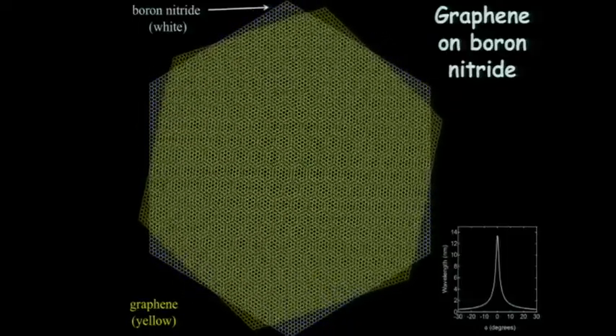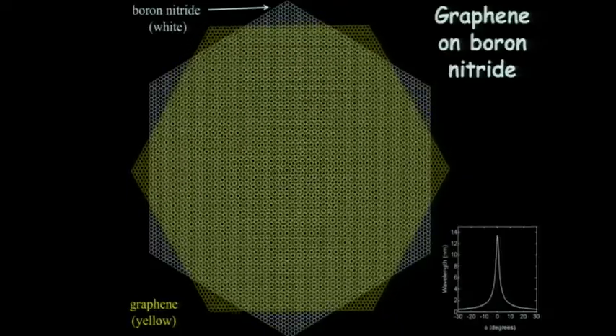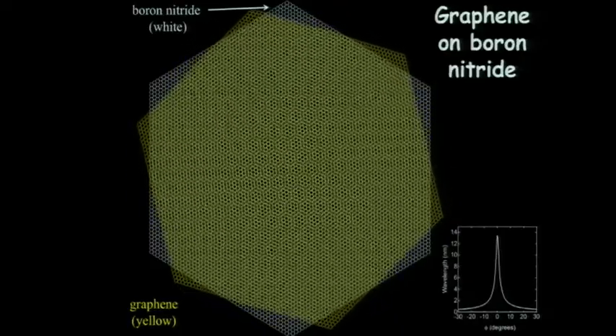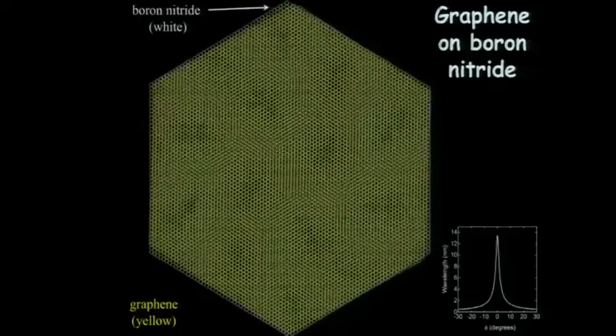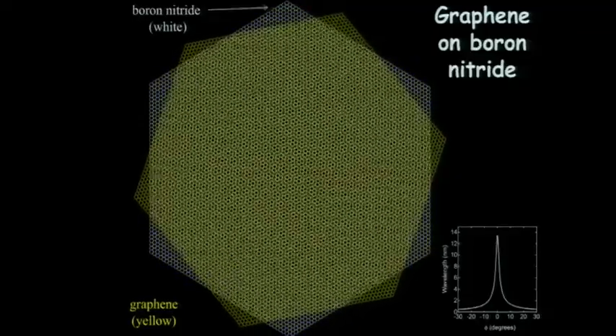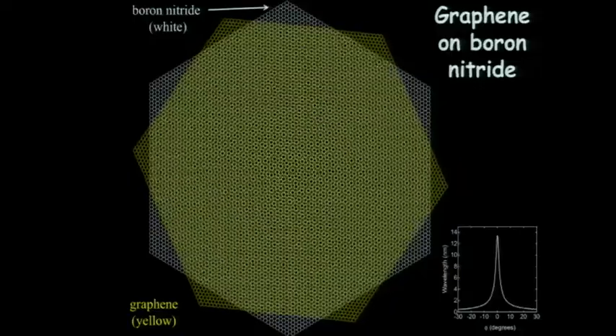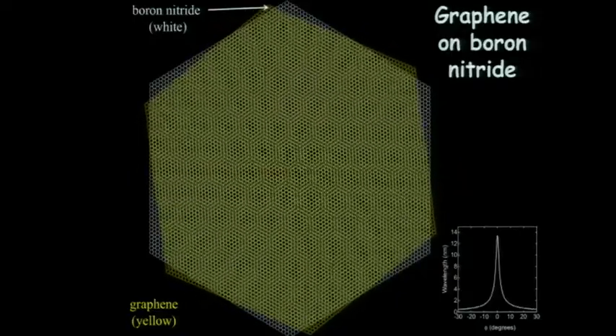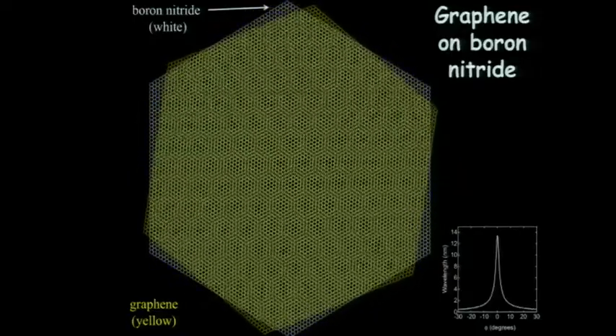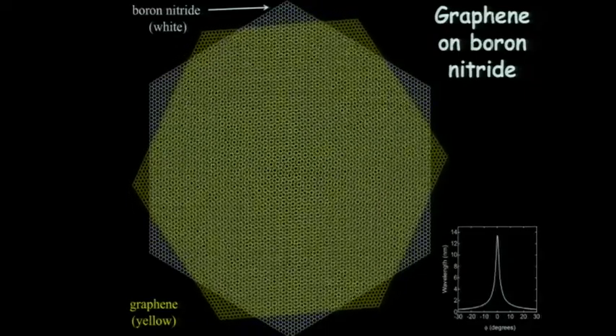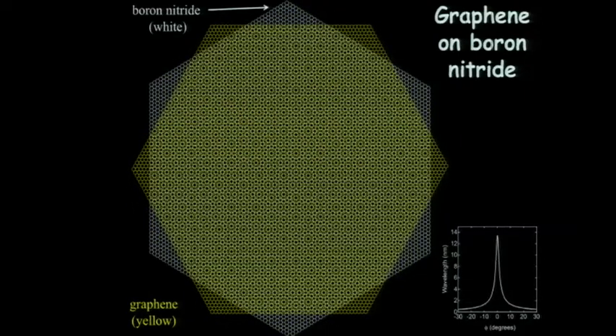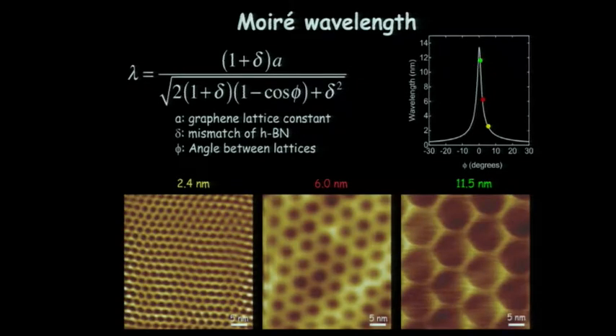So as you rotate it all around, you see them match up. You get a very long wavelength Moiré. As you get them about 30 degrees apart, you get a very short Moiré, and then it grows out here, and you can see a sort of twist as you go. Because the lattice constants are slightly different, there's a maximum of about 13, 14 nanometers that you can get here on the Moiré pattern. And so what we've seen here is that just by changing the twist angle, we can get all of these different Moiré patterns. And it's pretty simple to work out what the wavelength should be.